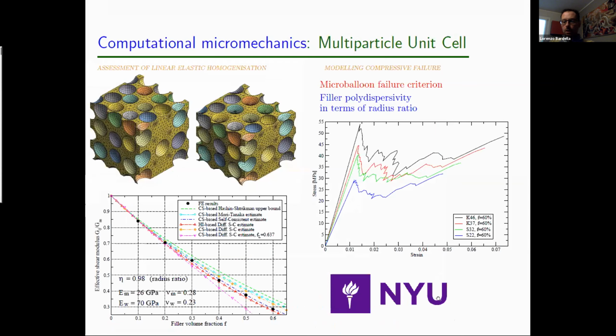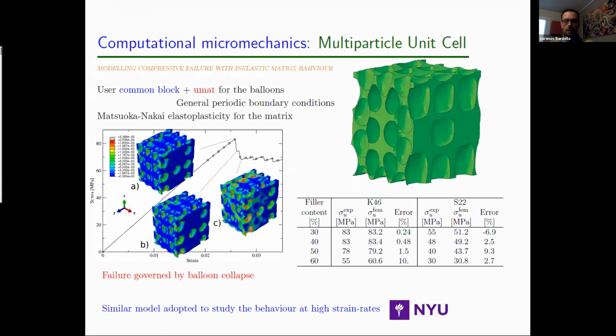Later, we started working with NYU, so with Nikhil Gupta, Maurizio Porfiri, and their students. And we started developing multi-particle unit cells. First, we used these multi-particle unit cells to critically assess the linear elastic homogenization procedures we developed. And then we used these models to understand something of the brittle failure under compression by plugging into these models a novel criterion for the failure of the microballoons. And then we extended these models with different nonlinear inelastic constitutive models for the matrix to understand some other behaviors like tensile behavior under high strain rate.